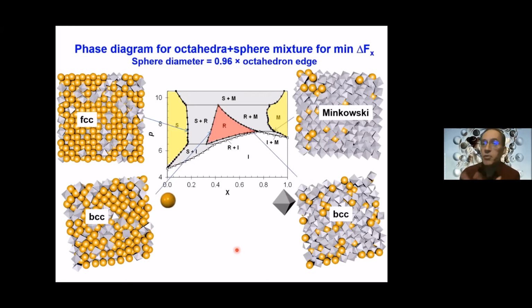And so it should be pointed out that we did not optimize for this phase. We didn't even know that this phase existed. But because we optimized the substitutional symmetry of the two components, somehow they found a new solution, a way how they could coexist in a solid solution behavior, which we found really interesting.